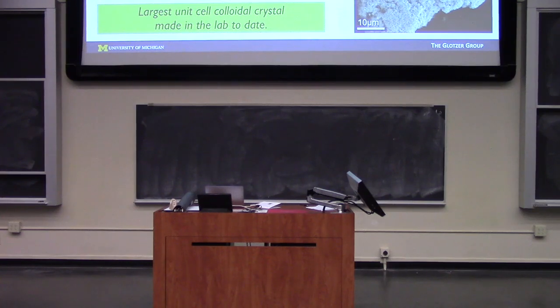And so that's what they thought, and then they sent us the pictures and we analyzed it and made a model of this, and then did molecular dynamics simulations, and were able to show that they actually have this clathrate structure, which I'll show you more about a little bit later. But with our model, we were able to predict exactly the same crystal structure. And in fact, if they change the length of the DNA and nothing else, they can get different clathrate crystal structures. There are different kinds. And in our model, we can also do the same and get the different crystal structures that they get. So this is a really complicated colloidal crystal structure, the most complicated one that I know of so far.